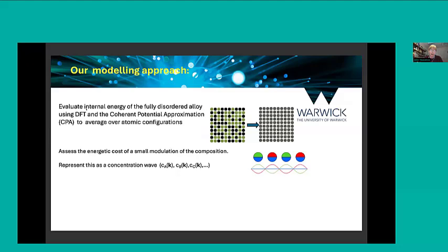disordered alloy based on density functional theory, but we're using an effective medium approach to describe the averaging over the atomic configurations. It's called the coherent potential approximation, and it's an old method for binary alloys, but now it's really coming into its own, we reckon, for these multi-component systems. So what it does is it sets up some effective potential that you place on every site in the lattice, such that the motion of electrons through that effective lattice mimics very well the motion of electrons on the average